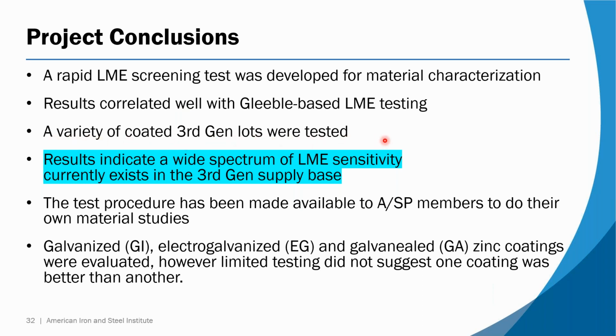We tested a variety of Gen 3 materials, and the results showed a wide spectrum of LME sensitivity in the supply base. We've made this test procedure available to ASP members, and we're making it available beyond ASP because we think that's the right thing to do. We want the material supply fixed so that anybody building a car should be able to rely on these new materials and not be constantly looking over their shoulder for an LME problem. We tested the 3 types of zinc coatings, the common ones: the GI, which is hot dip, electrogalvanized, EG, and then the galvanneal. There wasn't any slam dunk there that one's better than the other.